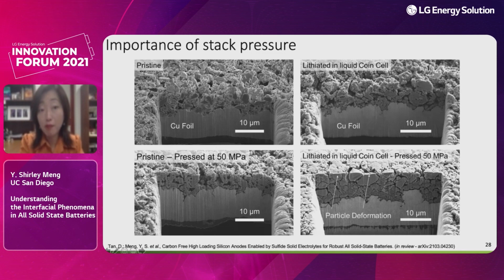Of course this is not optimized, but the good news is that you really do not see huge microstructure changes for the micron silicon. That behavior is completely different from the lithium metal case, because with lithium metal, if you charge the battery at 50 megapascal, you induce mechanically-induced shorting very effectively.